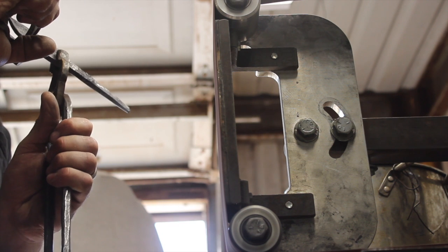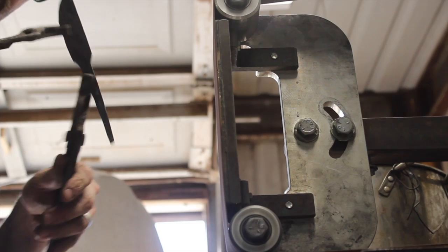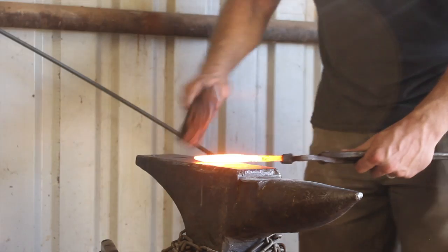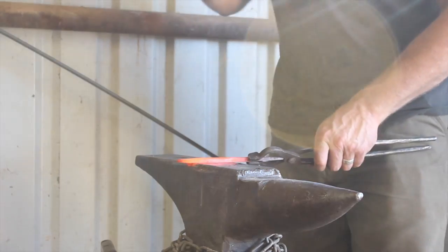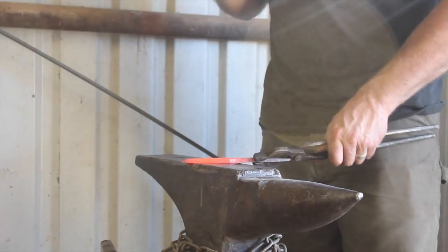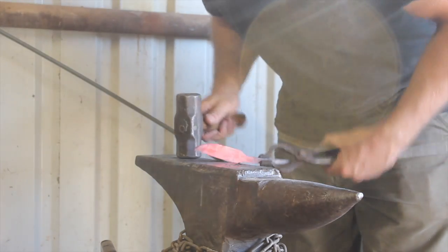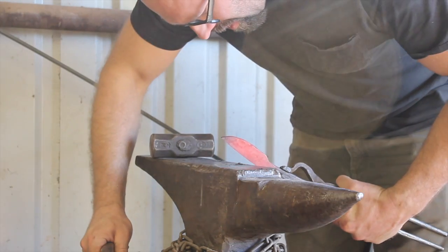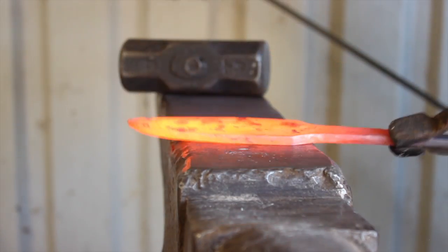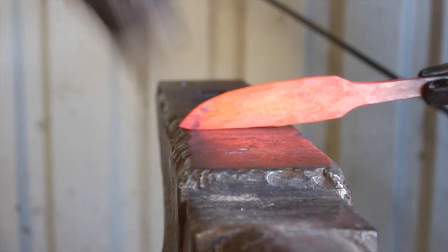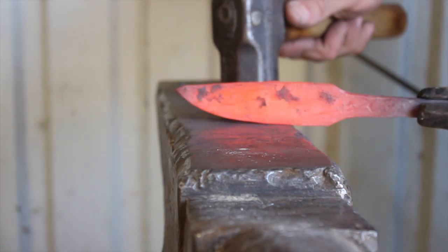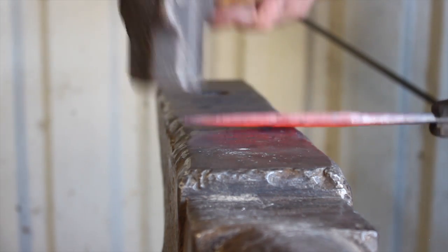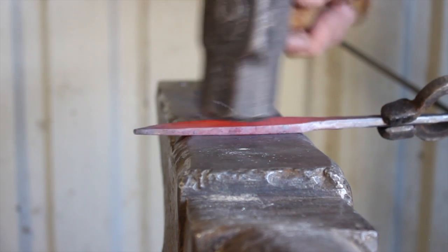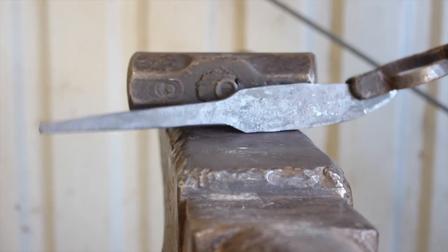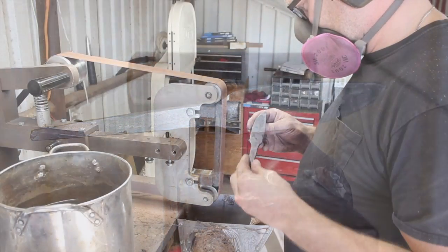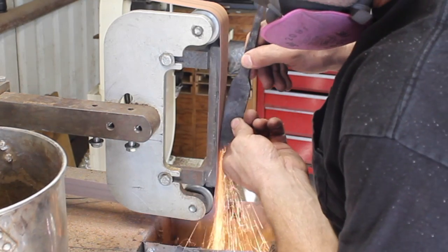So I'm grinding off the spine right towards the tip, which is where that forge weld line is at. And you saw as I was forging the blade, forging that tip down around to where the forge weld line from that V that we closed up terminates up on the spine of the blade, near the tip, but on the spine. And that ensures that you don't have a forge weld line anywhere near your edge, because even though we've got a good forge weld, it's going to be best case scenario to keep that away from the edge, and the tip as well. So we're about 3/8 of an inch back from the point of the knife with that forge weld termination. And there's the blade forged out and ready for some cleaning the profile up and rough grinding the blade.